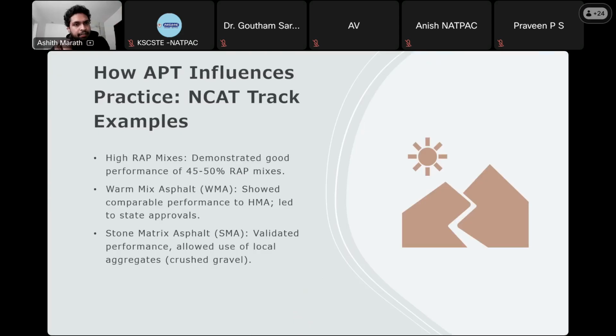Another application by the NCAT test track is that they used their APT facility to demonstrate high RAP mixture performance. They demonstrated good performance with 45 to 50% RAP usage in the mixes, and they also used the APT with warm mix asphalt pavements and showed comparable performance to hot mix asphalt, leading to state approvals. And they also validated stone matrix asphalt, which allowed use of local aggregates like crushed gravel for widespread use in the state.